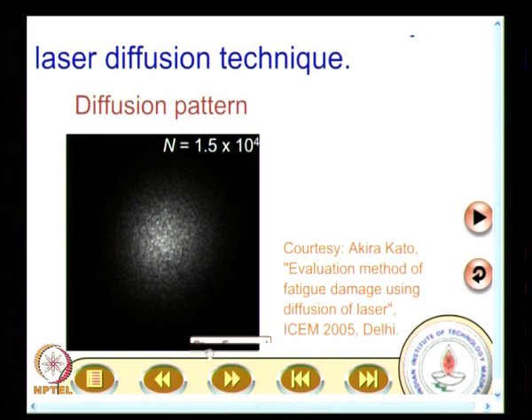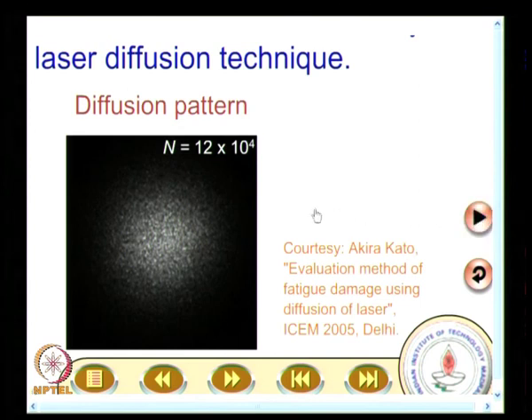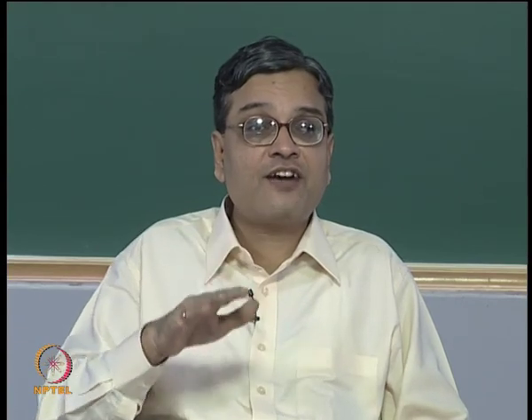And what you see here is a diffusion pattern for the cycle 1.5 × 10⁴. You see white dots here, which gives the diffusion pattern. This was published in 2005, and we will see what happens when the number of cycles increased. When the number of cycles increases to 12 × 10⁴, the size of the diffusion pattern has definitely grown. So, this is an indication that slip bands are formed, and the density of this fatigue damage increases after several cycles. So, this explains that cracks can form at the surface and go beneath, and then your Paris law comes to your rescue to find out how the crack will grow.